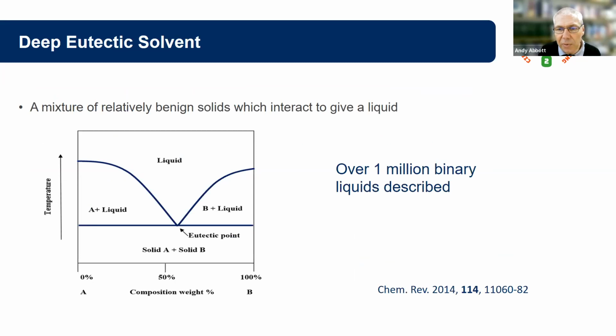And this is why I've been brought into this project. About 20 years ago, we came up with a way of making a solvent that didn't evaporate. You take two solids and mix them together and you make a liquid, and that's called a eutectic, which means "easily melted" from the Greek. Through a series of patents, we patented over 1 million of these binary mixtures, and we routinely use ternary and quaternary mixtures of components to make a liquid.